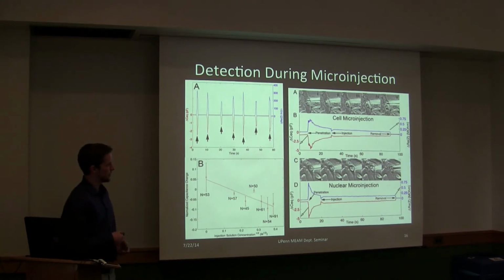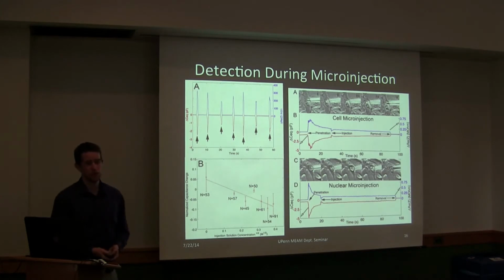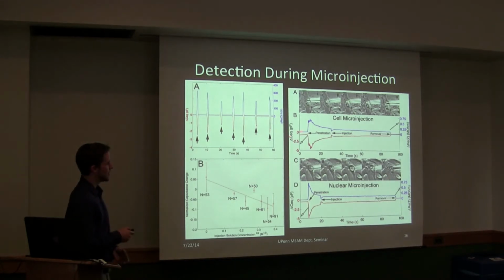We also looked at pulsed injection conditions. So here we actually apply a pulse of pressure to inject fluid into the cell. Again, the red curve is capacitance, the blue curve is the real part of the impedance, essentially the series resistance. And we can look at the penetration events, and then we can also detect the pulse that we apply for injection. And there is some back pressure applied to the pipette to prevent clogging, so that leads to this kind of gradual approach to a steady state condition as the cell is slowly injected. And we also looked at this curve over time to show the stability.